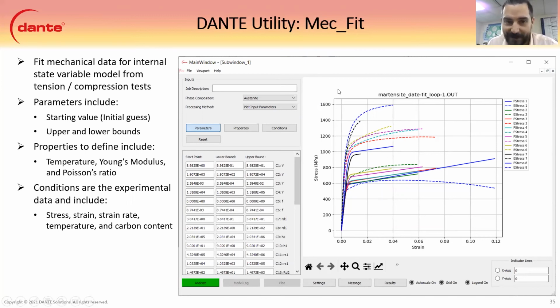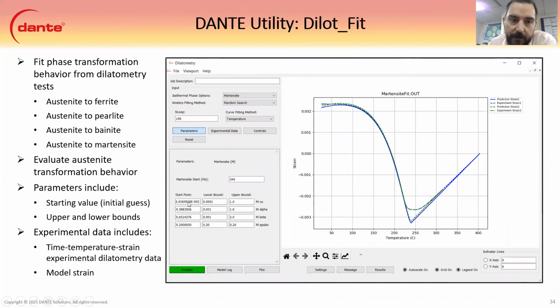So the mechanical properties can get a little deep as far as fitting. You define your temperature, your Young's modulus, and Poisson's ratio. Those are basically your elastic conditions, and then you fit your data for the plastic conditions. We use a fitting where there's an initial guess and then a lower and upper bound to control where you fit that data. The same thing with the Dilot_Fit. There was an initial guess and then a lower bound and an upper bound to fit to.